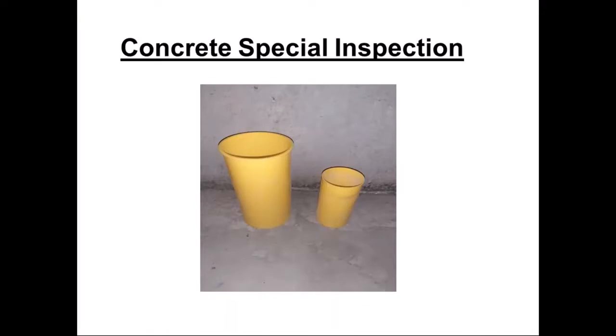This is an example of the test cylinders that the inspectors and testing agencies will use to fabricate concrete test specimens. So there's 2 types that can be specified. 6x12s on the left or 4x8s. With the 4x8s, 3 of these need to be tested at 28 days to verify concrete strength, whereas with the 6x12s, only 2 are required to verify the concrete strength.